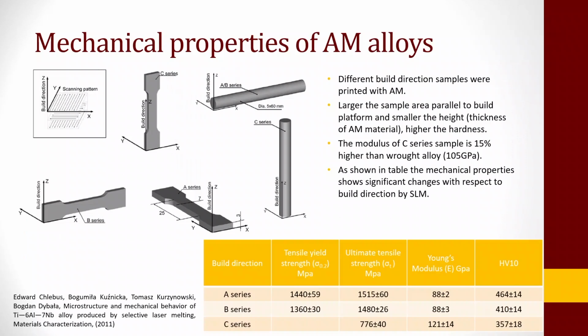Now, as I said, microstructure really determines the mechanical properties of the materials. All of these mechanical properties also depend on the build direction. So I have 3 different types of builds, which I have labeled here as A series, B series, and C series. Depending on how you build, so this is a regular dog bone shaped tensile testing specimen, and you could see in the little table below that you can get a very high ultimate tensile strength in the A series as compared to B and C series. Similarly, the Young's modulus is very high for C series as compared to A and B series, and so on and so forth. Which basically tells you that your mechanical properties are also going to vary depending on your build direction.